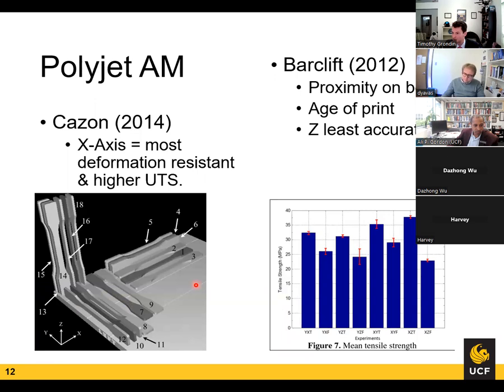We've got two specific people we're going to talk about with similar research, but different findings. Cazon, in 2014, produced two different samples, 9 each, on an Objet Eden 330 and a FullCure 720 material. He was specifically addressing tensile testing for ultimate tensile strength, as well as surface roughness. His sample and printing orientations are shown right here in the lower left-hand corner, and they were all printed as solids. There was no change in density, there was no change in core.